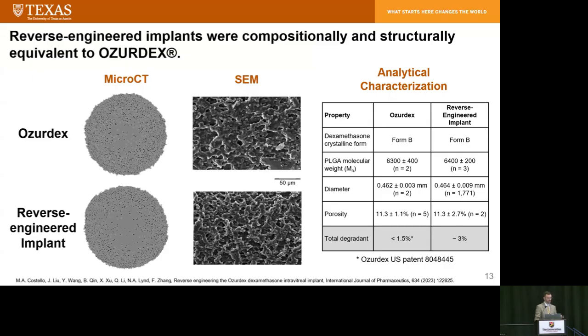By SEM, we looked at the surface morphology. The drug remains in the same crystalline state. It doesn't melt, so you'd expect that the starting form and the form in the final product are the same. PLGA molecular weight in the finished product was the same as in Ozurdex. And then I already discussed diameter and porosity.